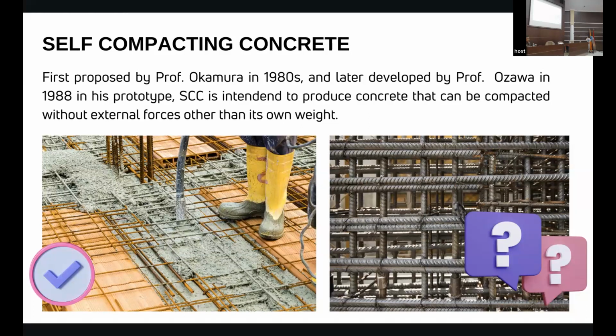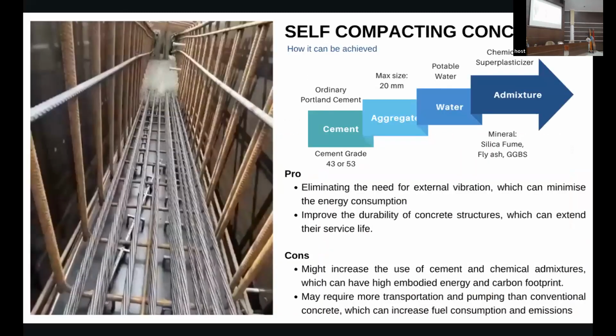Your rebar can get exposed, or your concrete can be quite porous. So you have to make sure the concrete can flow, filling into the rebar, this rebar jungle. Right. This normal concrete, you can just use a poker vibrator, just to make sure all the concrete will flow into each part of the formwork. But for this jungle of rebar, it will be too difficult. In this way, you have to use SCC.